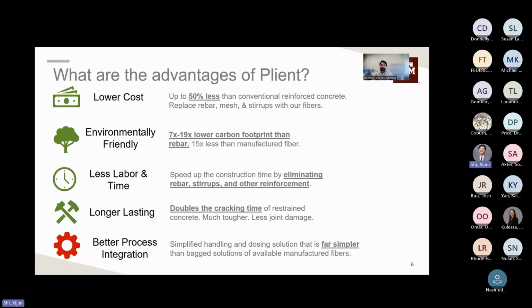Additionally, because it's a recycled product, the second key advantage is the environmental impact. Because this is a recycled product that's replacing a manufactured rebar or steel fiber, there's a 7 to 19 times lower carbon footprint associated with Plient concrete compared to rebar. Additionally, there's a 15x lower carbon footprint of the Plient fibers compared to some of the manufactured steel fibers.